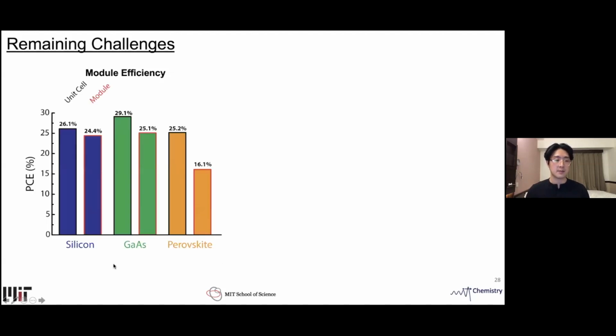On the left, I'm showing power conversion efficiency of silicon, gallium arsenide, and perovskite solar cells, with the unit cell and module shown as these two columns. For silicon and gallium arsenide, the efficiency of the module is not too far behind that of the unit cell. However, when it comes to perovskite solar cells, the efficiency of the module is significantly lower than that of the unit cell.